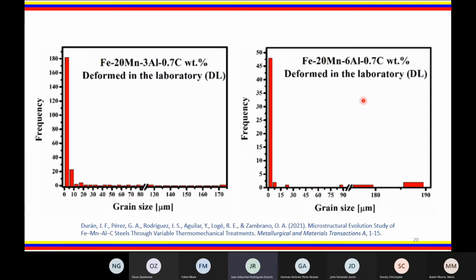In order to quantify the effect of dynamic recrystallization, this grain size distribution was performed, in which the distribution clearly indicates that at one deformation step in both alloys, there is a process of formation of new extremely fine grains.